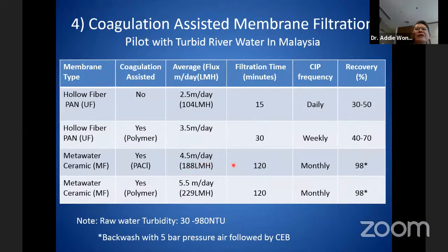So filtration time, we can lengthen up to 120 minutes compared to 30 minutes. So the CIP we need to do is like monthly. So the recovery we can go to 98%. Of course, for this 98% we need the so-called backwash with 5 bar pressure, and then followed by CEB. And this is all in an auto system.